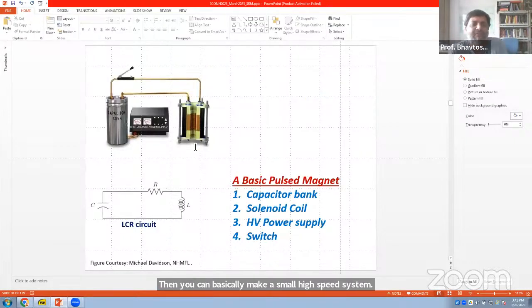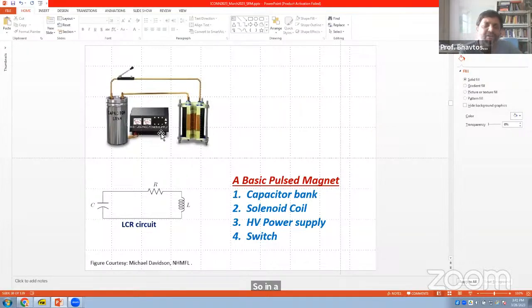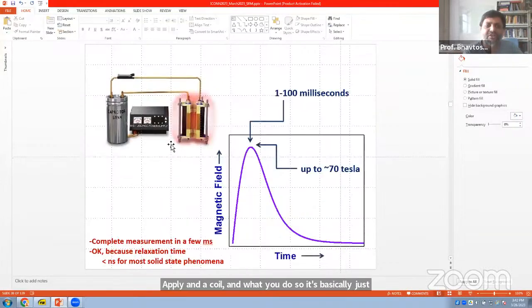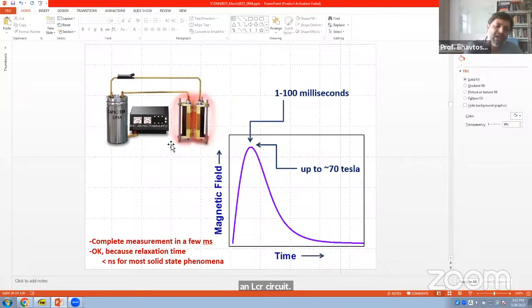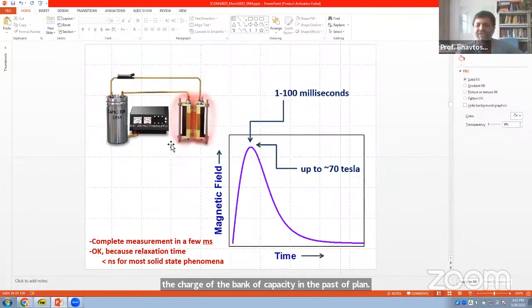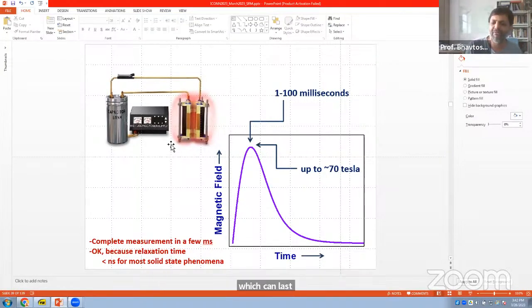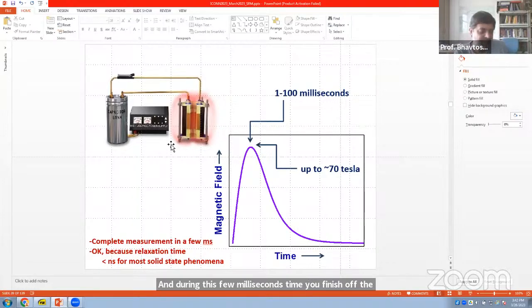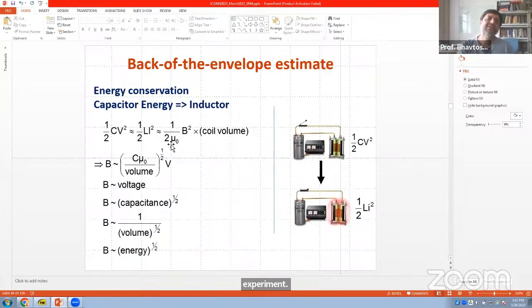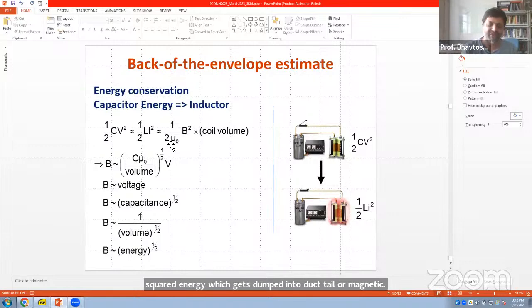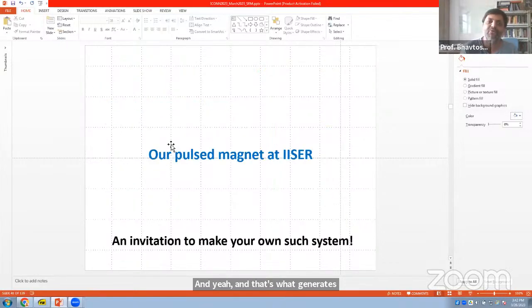So in a pulse magnet, what you have is basically a bank of capacitors, a power supply, and a coil. It's basically just an LCR circuit. You charge up the bank of capacitors with the power supply, and close the switch. As the switch closes, you generate a large transient, which can last up to a few milliseconds. During this few milliseconds, you finish off the experiment. So you have half C V squared energy, which gets dumped into inductive or magnetic energy, and that's what generates a large transient field, and during this time you do the measurement.